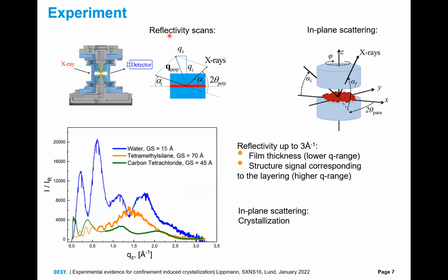In the experiments, we measure the reflectivity, perform reflectivity scans and in-plane measurements. In the in-plane measurements, we shoot with the beam through the gap and put the area detectors, or we perform in-plane scans. From the reflectivity, we measure the film thickness, and we also extend the reflectivity to higher Q values because we are also interested in the signal coming from the layering.